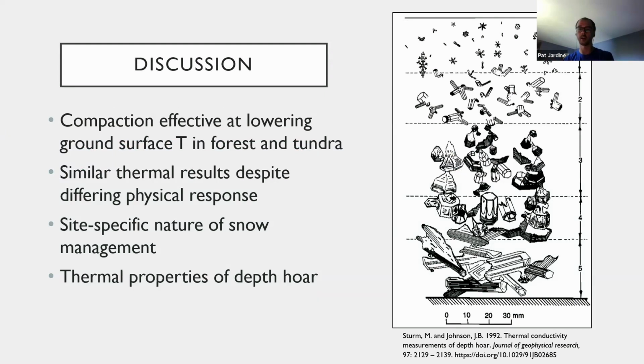So looking at what's going on here, it's a bit difficult to compare between the sites directly, given this difference between them. But I think one key takeaway is that they're effective for different reasons in different locations. In Mayo, it was pretty straightforward. All the snow was soft and it got smushed. But at the Dempster sites, only the depth hoar layer got smushed, and this suggests that the depth hoar layer has a disproportionate influence on the thermal conductivity of the snowpack, even beyond what would be expected based on its low density. The idea that the depth hoar layer generally has low thermal conductivity is commonly accepted, but the exact extent of the low thermal conductivity appears to have some uncertainty.